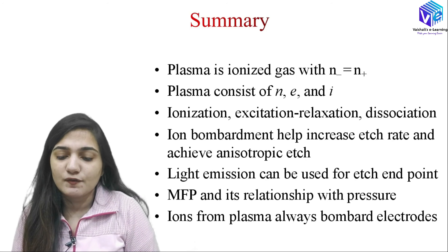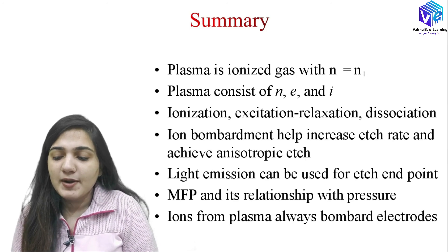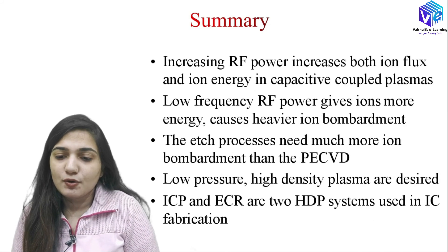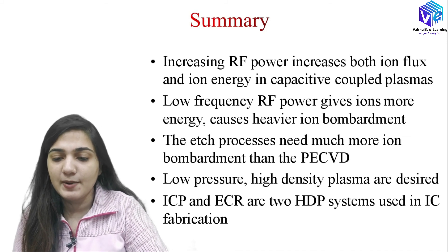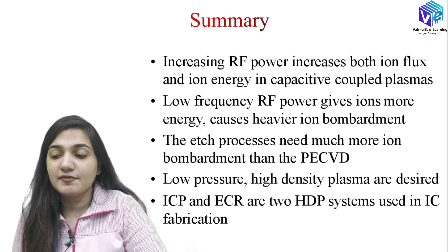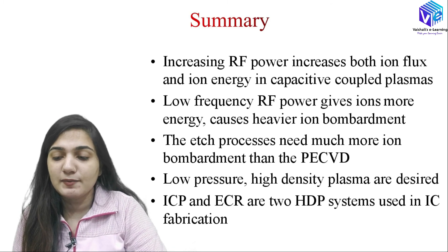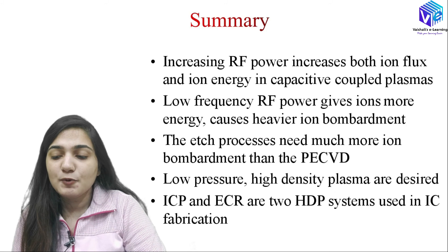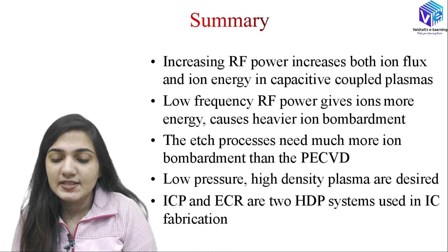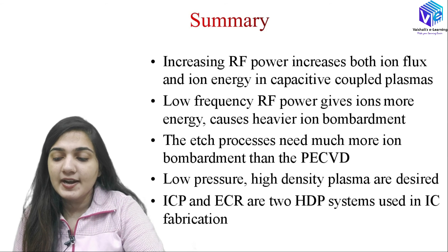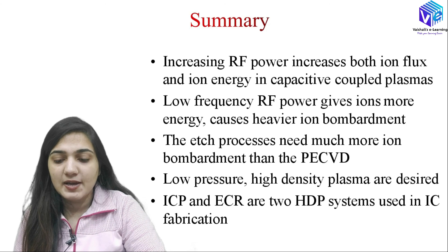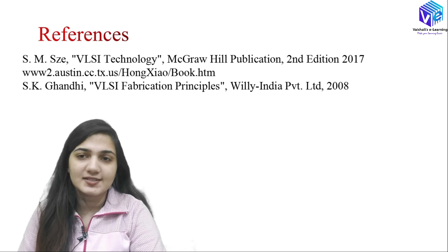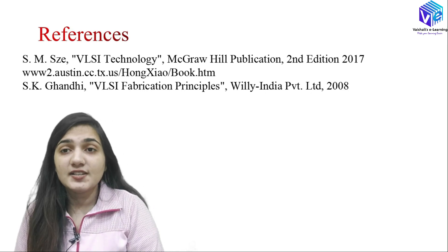Ions from the plasma always bombard the electrodes. Increasing RF power increases both ion flux and ion energy in capacitively coupled plasma. Low-frequency RF power gives more ion energy, causing heavier ion bombardment. The etch processes need much more ion bombardment than PE-CVD processes. At low pressure, higher density plasma is desired, and ICP and ECR are the two high-density plasma systems used in IC fabrication.